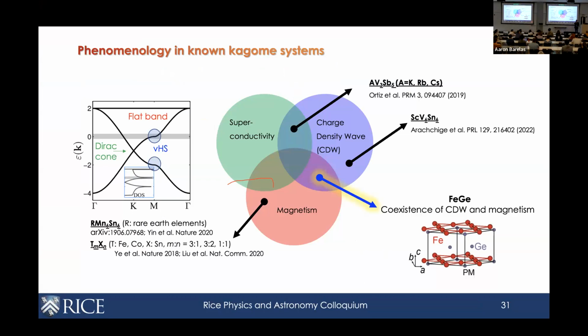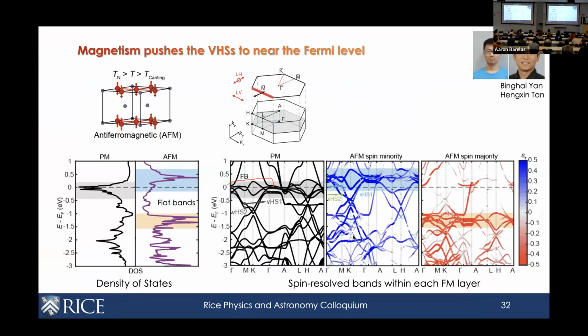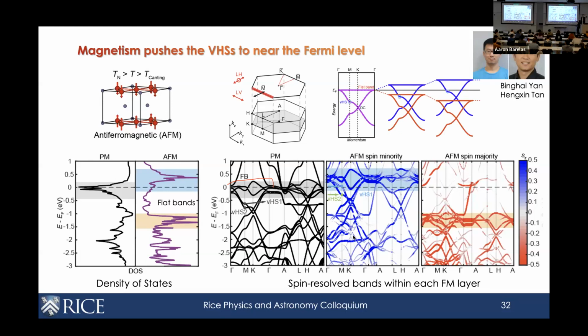But I think the question is, why does magnetism happen first and then charge density wave? According to this picture, the reason is that you think about charge order arising out of the magnetic phase, which arises out of the non-magnetic phase. If you calculate the band dispersions in the non-magnetic state, the flat band is living at the Fermi level. Then when the magnetic order sets in, you have spin majority and spin minority states that split, such that the Van Hove point, which used to be living far away from the Fermi level, now gets lifted up towards the Fermi level. So the Van Hove point is there when the CDW order sets in. It's only because of the splitting caused by magnetism, yes, that's the implication.